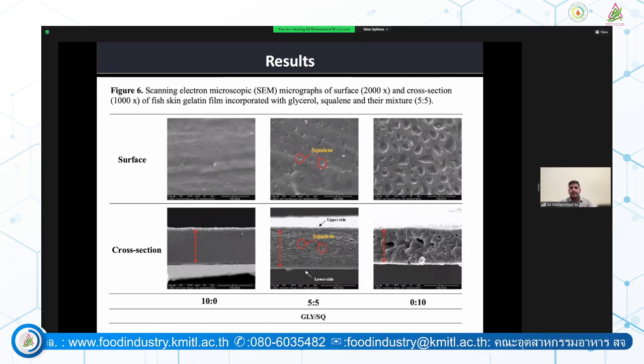But at the higher proportion without glycerol, we can see there is no proper droplet distribution and no good surface of the film. So this could conclude that glycerol at some proportion is very much necessary to prepare the film with flexibility and with homogeneous distribution of squalene.